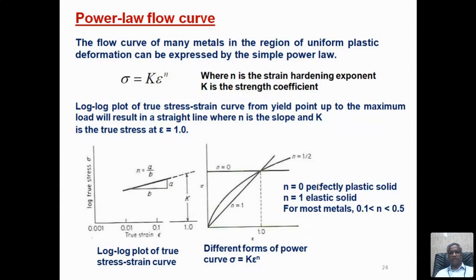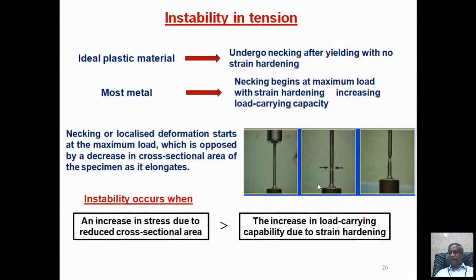How will you get the true stress, true strain curve? From the engineering stress, strain curve, convert that engineering stress into true stress, engineering strain into true strain, and plot the graph. That curve is governed by the flow curve equation. The slope of the curve is the strain hardening exponent, and the intercept of the curve is the strength coefficient. Right, so this is instability in tension, because the ideal plastic material undergoes necking after yielding with no strain hardening.